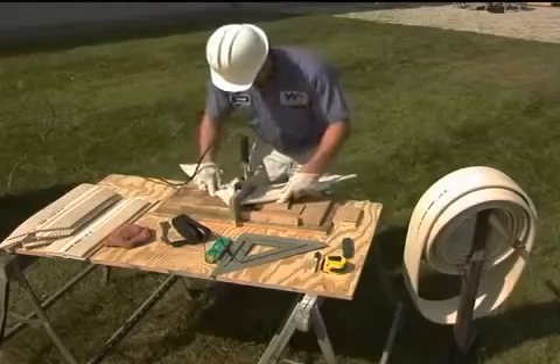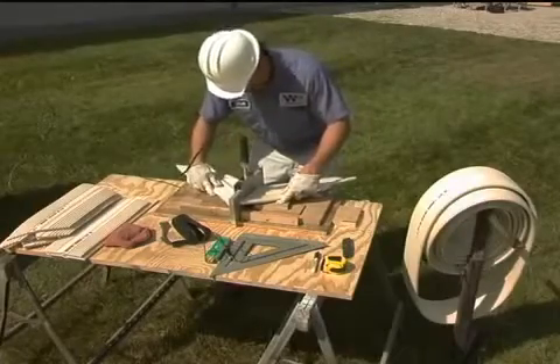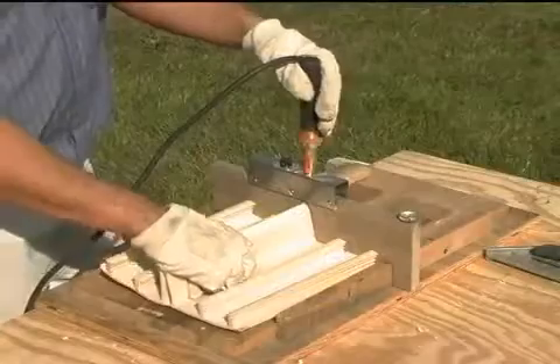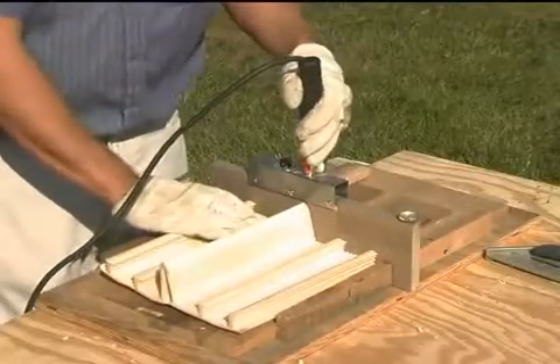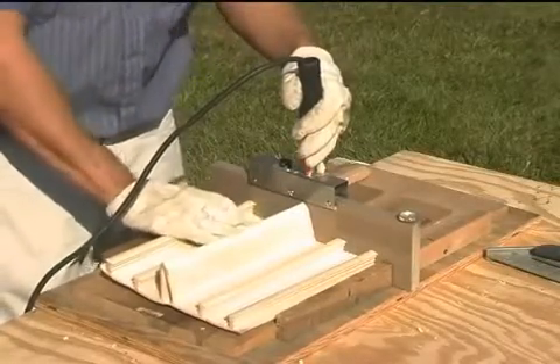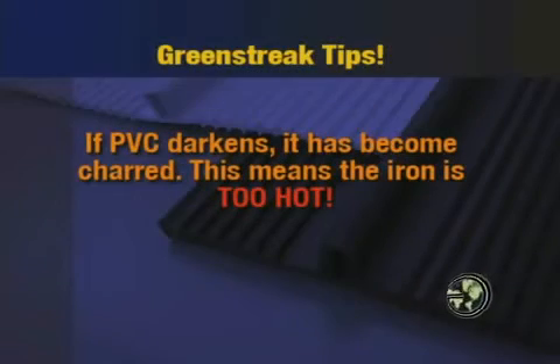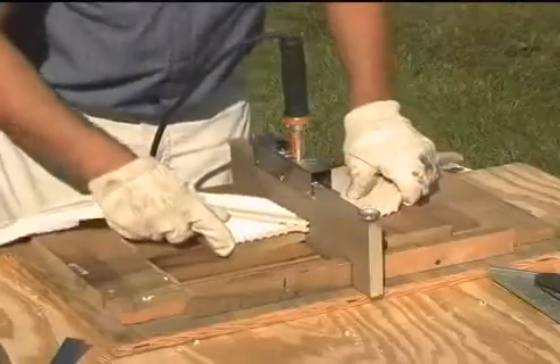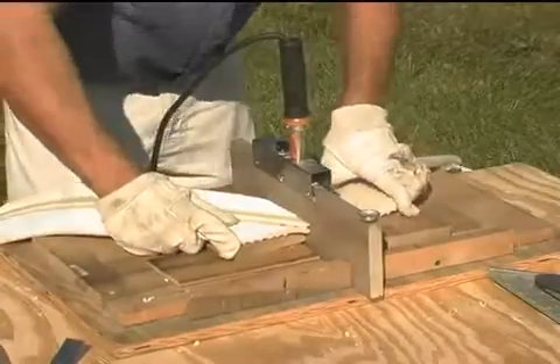Simply take a piece of PVC water stop and hold it directly on the face of the iron. If it appears that the water stop is melting within 20 or 30 seconds, the iron should be hot enough for welding. Green streak PVC water stop should not significantly darken when melted. If it has, it's an indication the welding iron is too hot and the water stop has been charred. Once the iron is at the correct temperature, you're ready to start welding.